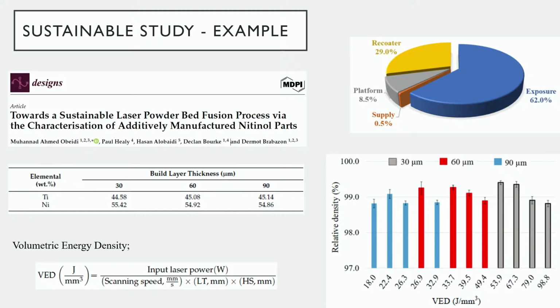Usually we use the volumetric energy density because we are using power. And these three very important variables: the scanning speed, the layer thickness, and the hatch space, which is the distance between two consecutive tracks of the laser beam. And then I calculated the density.